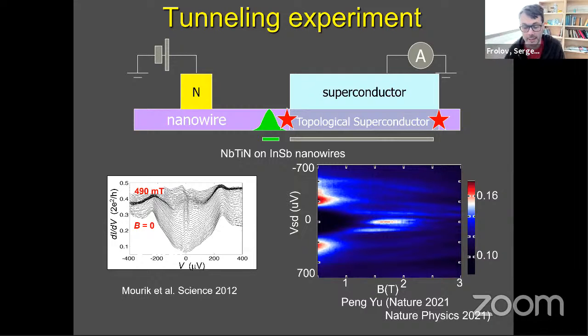So as an induced superconducting gap, you can see that inside the gap, conductance is suppressed. Oh, it's not zero, but it is suppressed. And then all the traces are offset for clarity, and they're for different magnetic fields, about 10 millitesla steps. So at around 100 millitesla, when we add magnetic field into the mix, we start seeing the zero bias peak feature. And one of the most interesting things about it that we noticed right away was that once it appears, it doesn't move away from this point that it appears in zero bias.